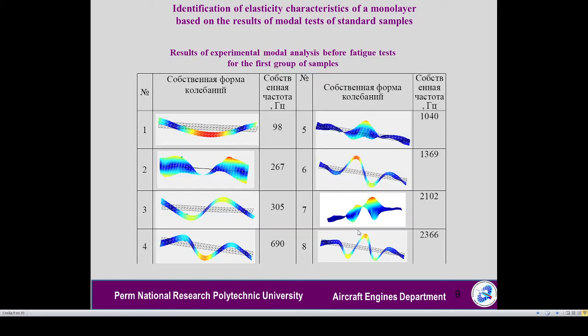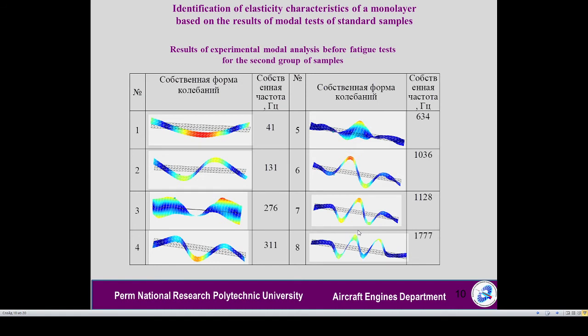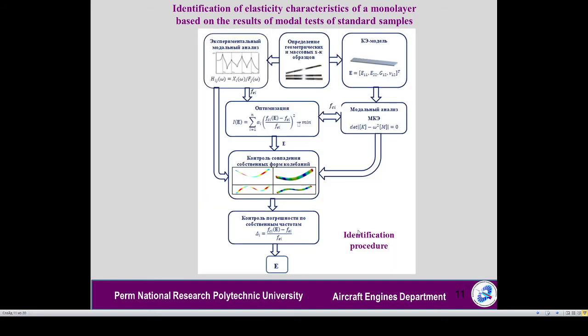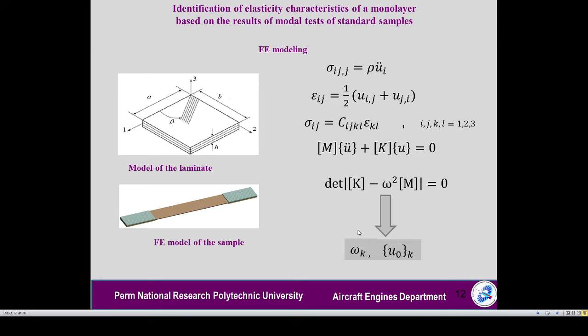The results of modal analysis before the fatigue test for the first group are shown on the slide. The results of modal analysis before the fatigue tests for the second group are also shown on the slide. On this slide, we can see the scheme for identifying the elasticity characteristics of a monolayer based on the results of modal tests of samples. A finite element model analysis was used to identify the elasticity characteristics. The main idea and FE model are shown on the slide.